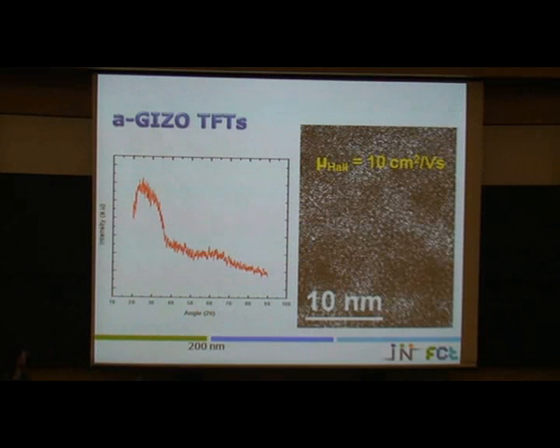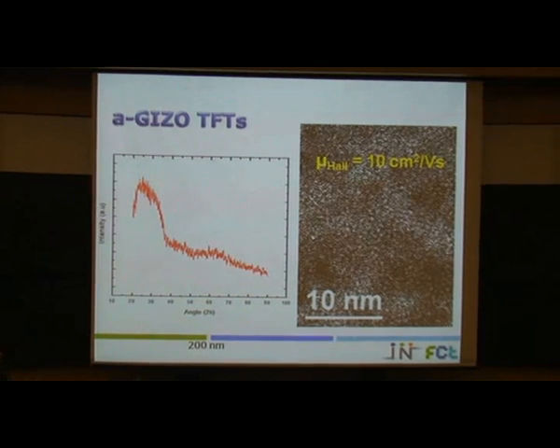So we have also performed other TFTs based on another system, gallium indium zinc oxide. Why do we use gallium? Why do we add gallium to the system instead of using IZO, indium zinc alone? It's because for IZO it's difficult to control the carrier concentration. It's very hard to control the number of carriers. And we use gallium just to lower a little bit the conductivity of the material, and in this way it's easier to control the carrier concentration.